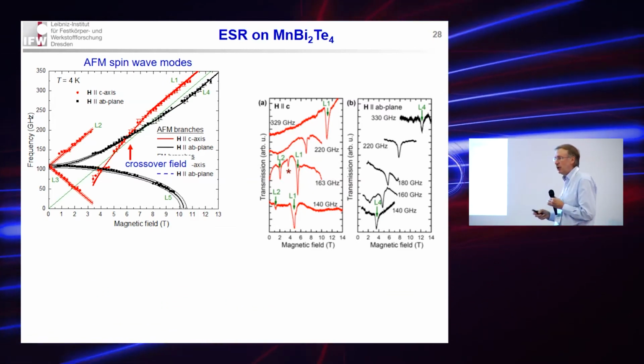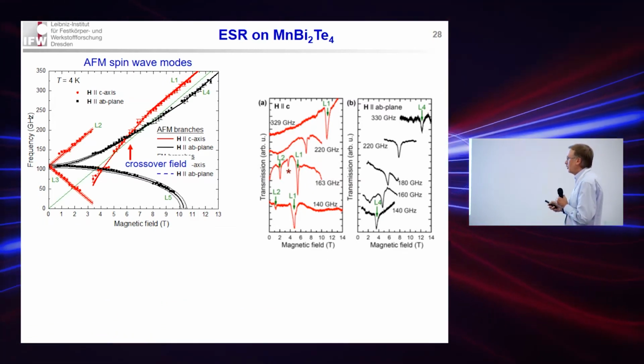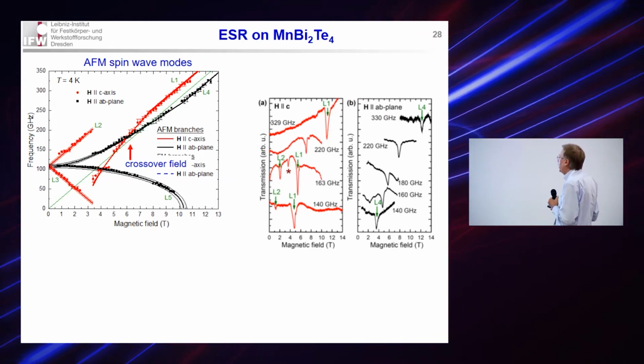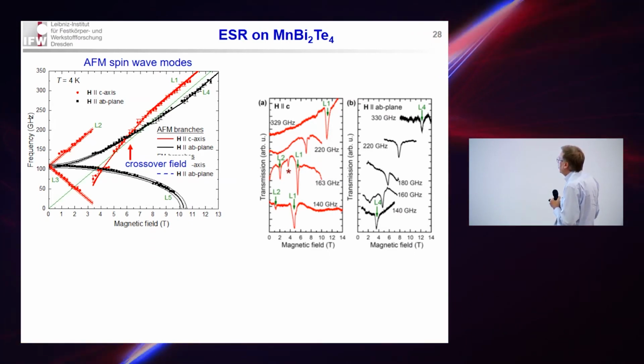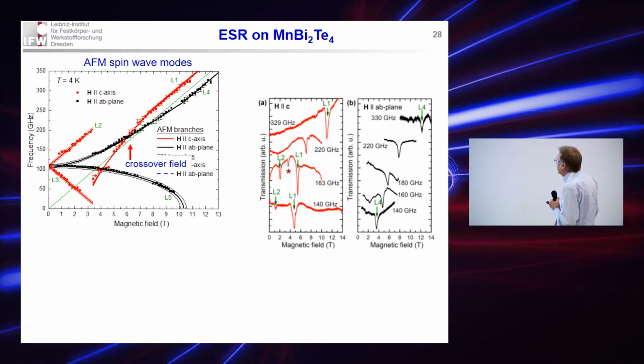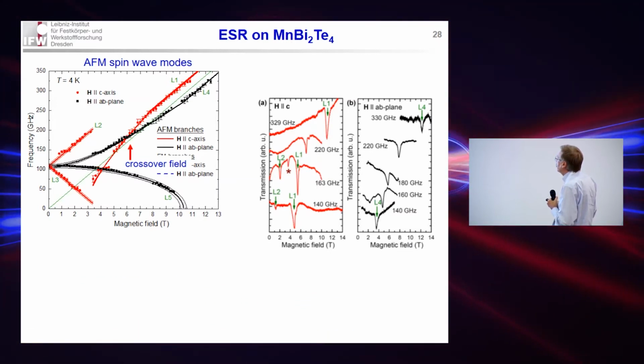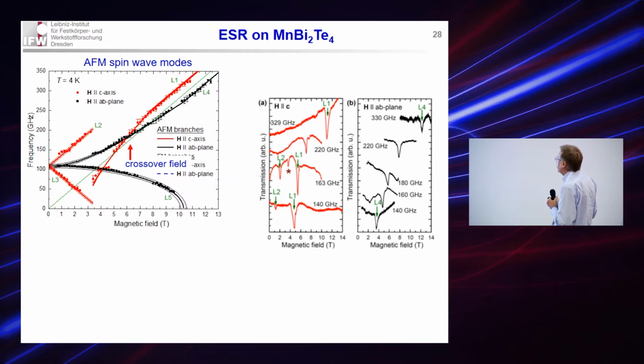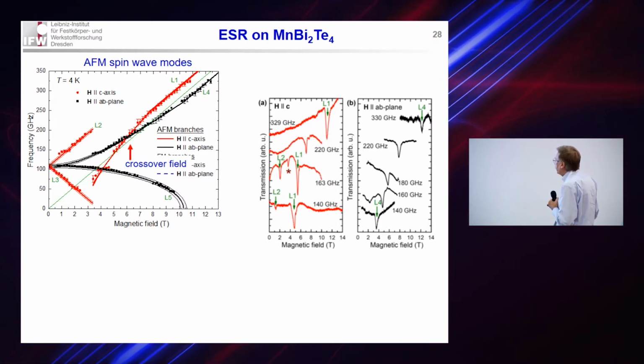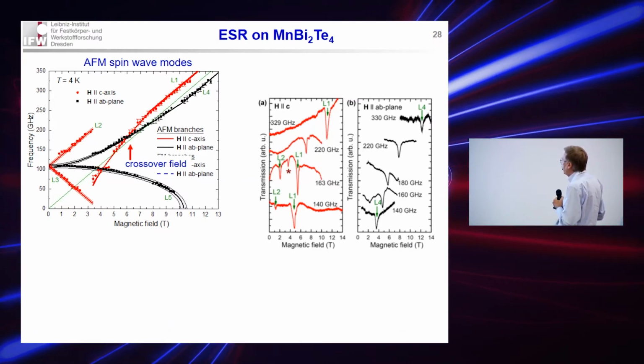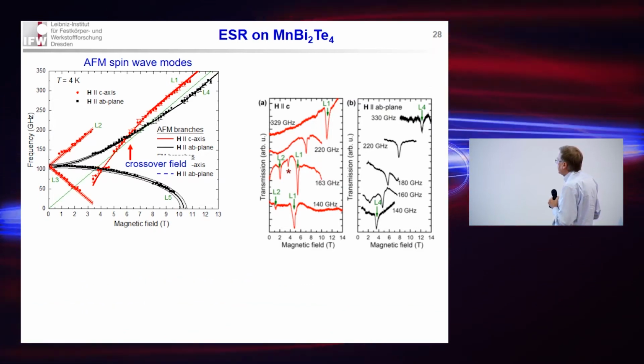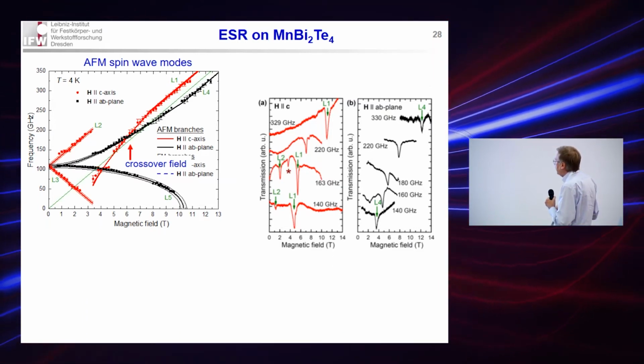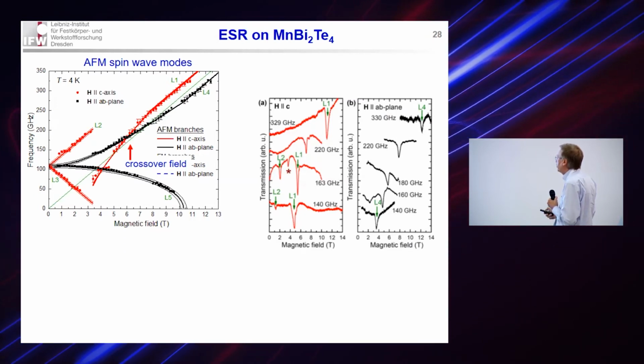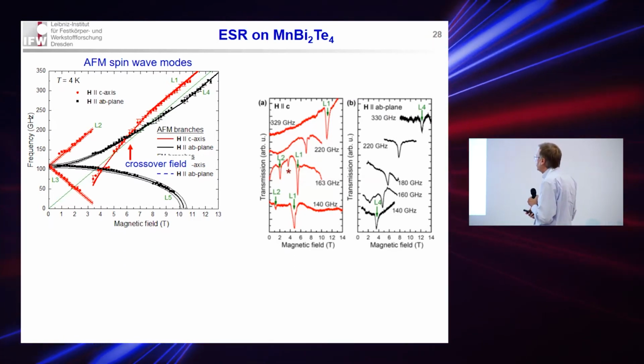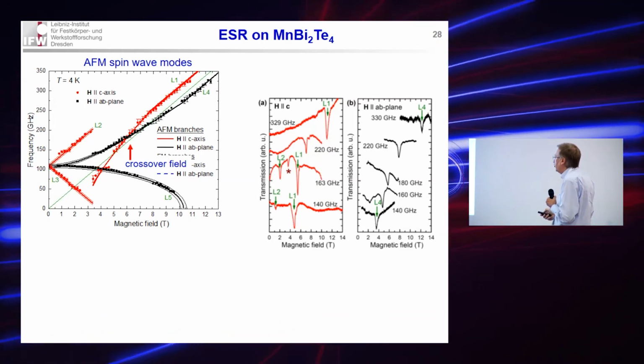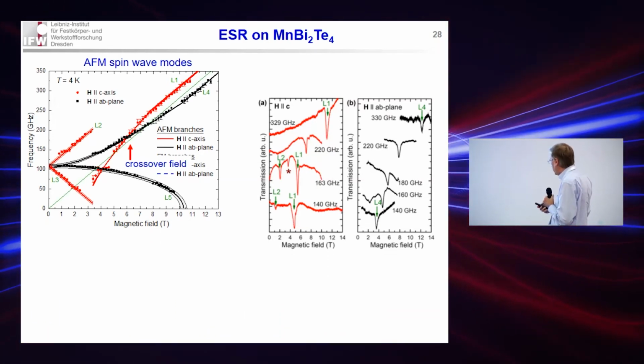And this is extremely unusual because in a conventional collinear antiferromagnet, this in-plane mode should approach the paramagnetic line from above, but never cross it, only approach it asymptotically. The other mode, the red one, for the out-of-plane orientation, should also approach the paramagnetic line at higher field asymptotically, but never cross it. But here we observe a crossover field, which turns out to be very specific for this 1-2-4 compound.